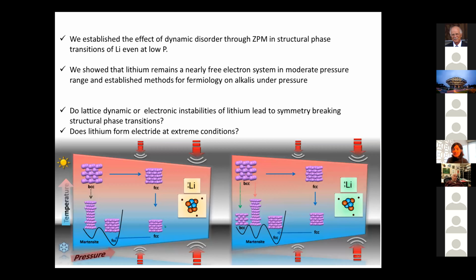As of now, we established the effect of dynamic disorder through zero-point motion in the structural phase boundaries of lithium, and we showed that lithium remains a nearly free electron system, not as much as sodium, but in moderate pressures. And we established methodologies that we can use to extend the range that we are looking at this Fermi surface of these alkalis to higher pressures.